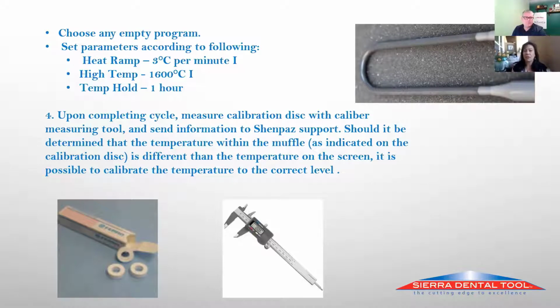So basically you would get a zirconia ring to sinter. You would sinter it at 3C per minute up to 1600 Celsius and hold it for an hour. This instruction is specifically for the Sintra Plus. This is what I had on hand. But most furnaces are similar. They may be a little bit different of a program, but this is the basic.